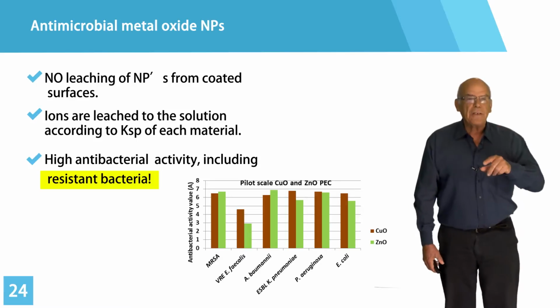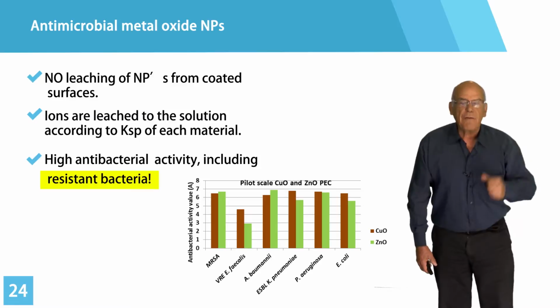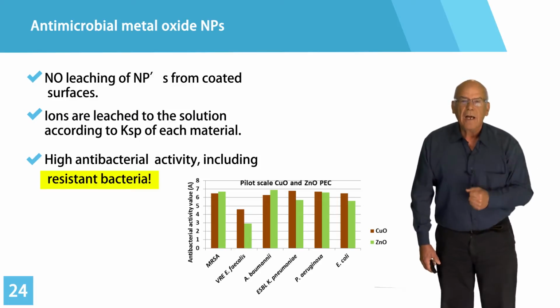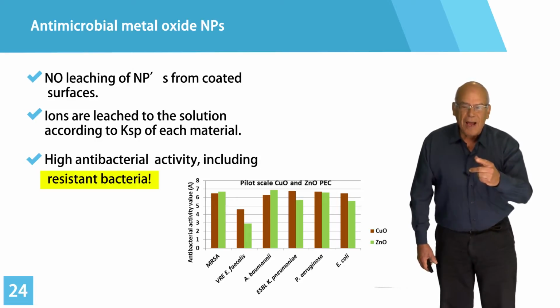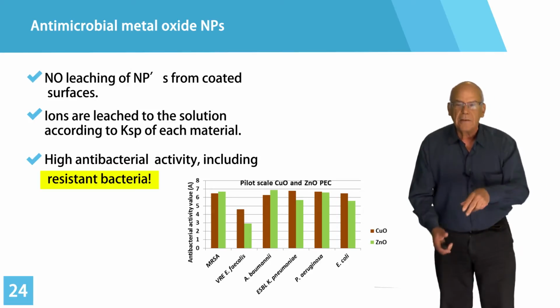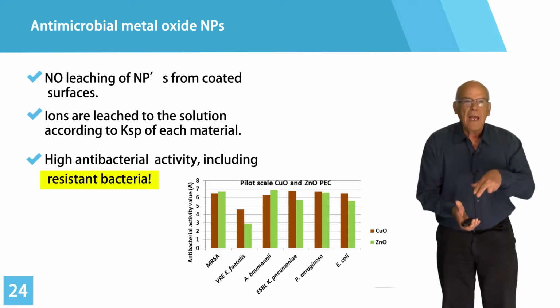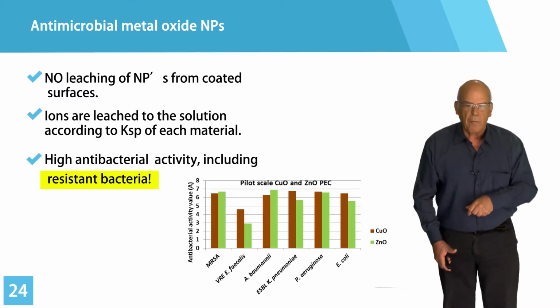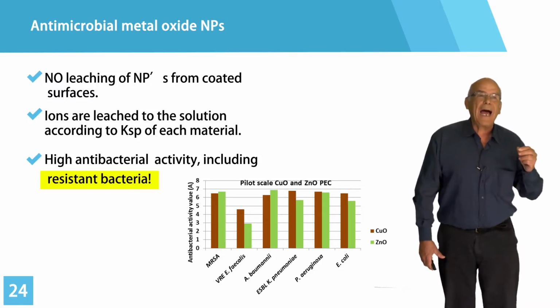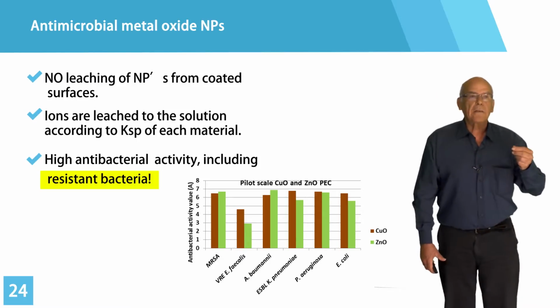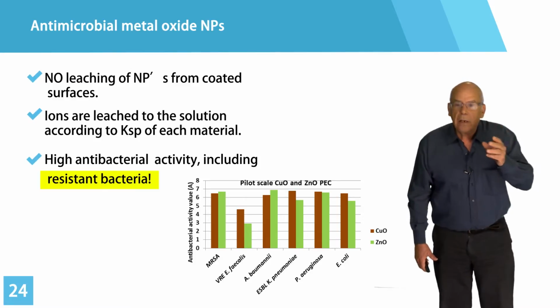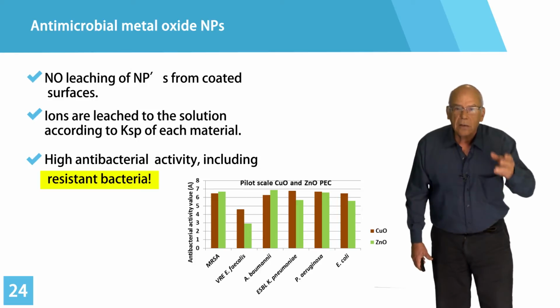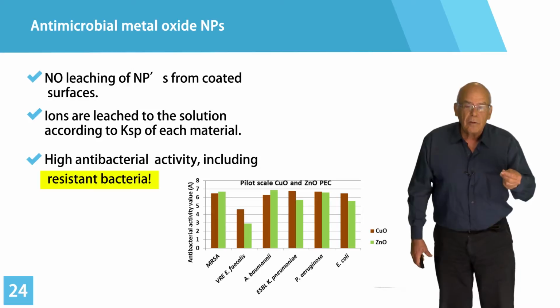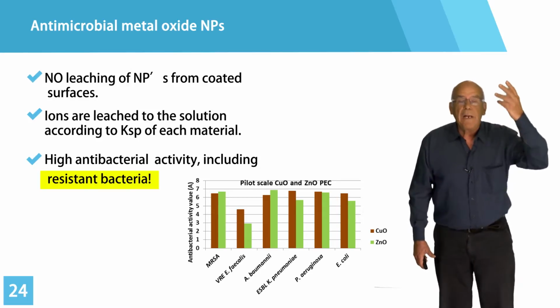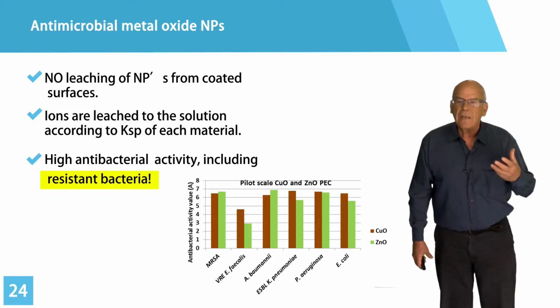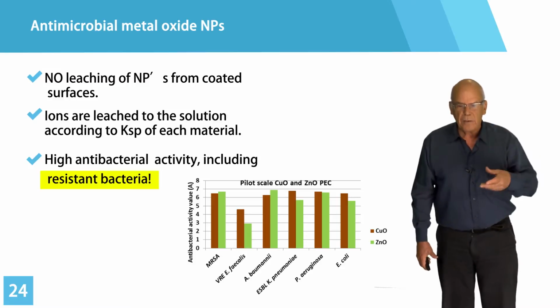These coated surfaces, let's say in the case of textile, were washed 65 times in a hospital washing machine. Hospital washing machine means 75 or 92 degrees centigrade. And after this long process, the nanoparticles were still on the textile and were showing very, very good killing of bacteria. What can be leached is the ions, namely copper ions and zinc ions. First of all, let me remind you that every morning when you eat cereal, you have zinc ions in your cereal, which is not bad. Secondly, the amount is dependent on a chemical equilibrium constant called KSP, and this equilibrium constant is very small, so the number of ions is very, very small.